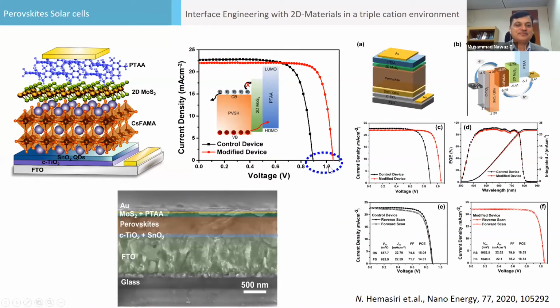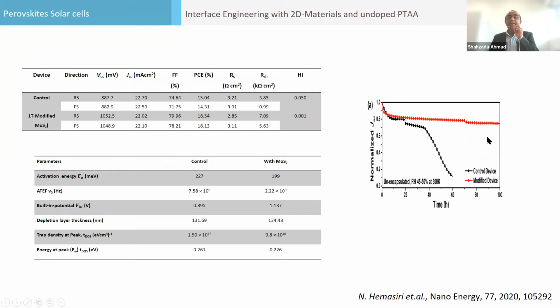Okay, so the voltage significantly increases, and this also increases the performance of the devices. The performance is close to 19%, and this is one of the best because it's dopant free. There is no dopant used in the PTAA. But the significant part was that the device stability increases to a much larger extent because 2D materials are more robust, and hysteresis also decreases significantly.